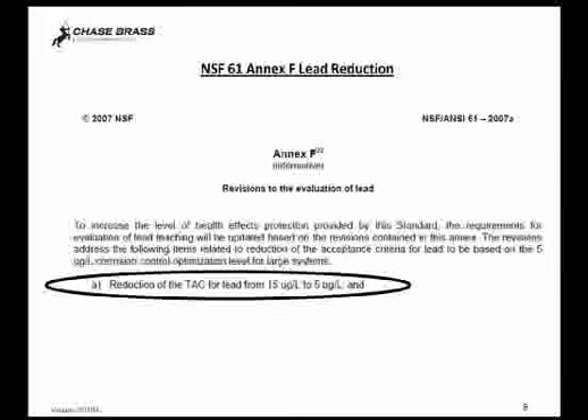on them. And this requirement to drop, as it shows in the oval at the bottom, the amount of lead that can leach into drinking water in their standard laboratory test from 15 parts per billion to 5 parts per billion was first voted in 2007, but producers were given 5 years to comply. And the hope here was that by having a tighter lead leachate requirement, that would supersede any form of additional state or federal requirements. But as you can see now, there's the double impact of 5 parts per billion and that weighted average lead maximum of 0.25%.